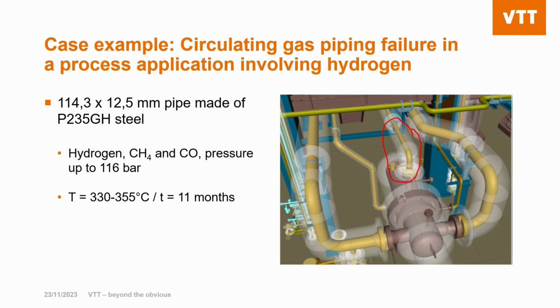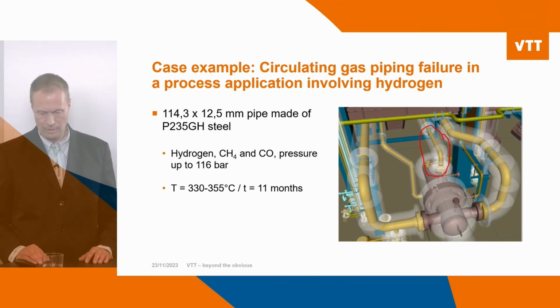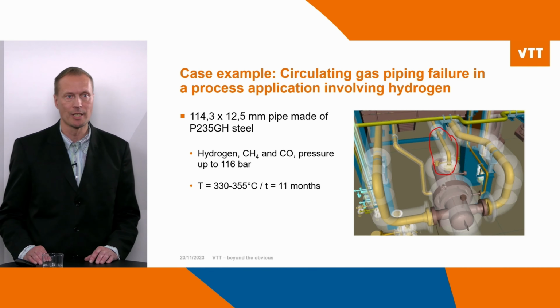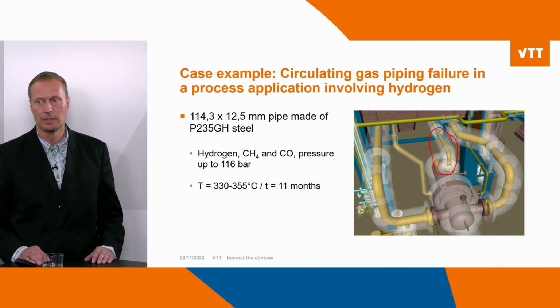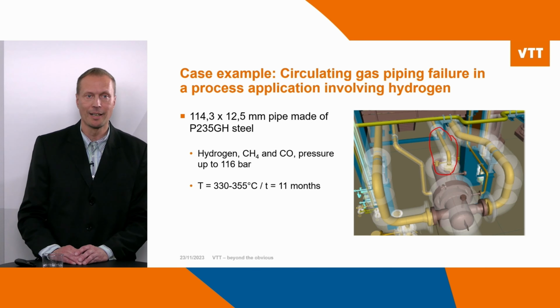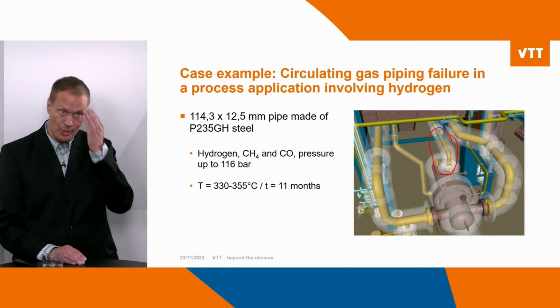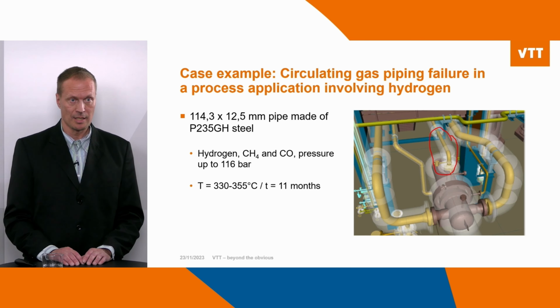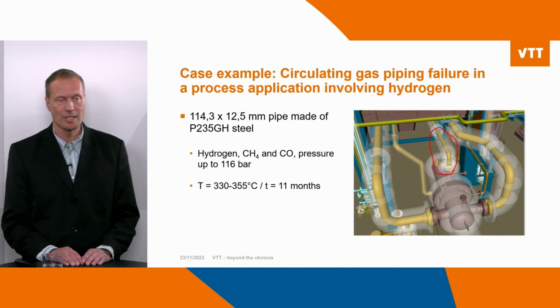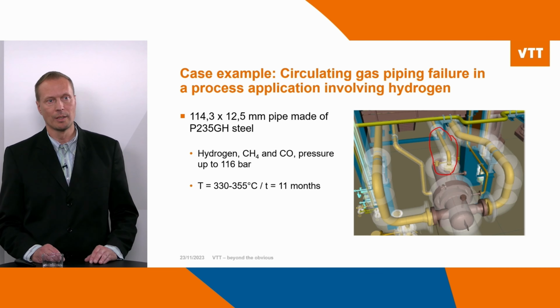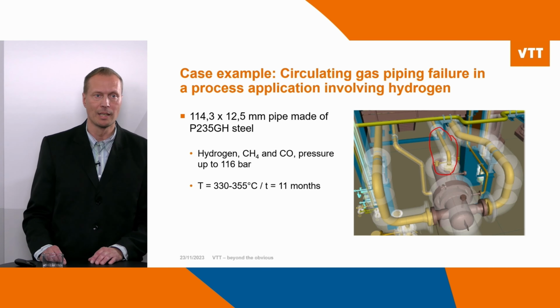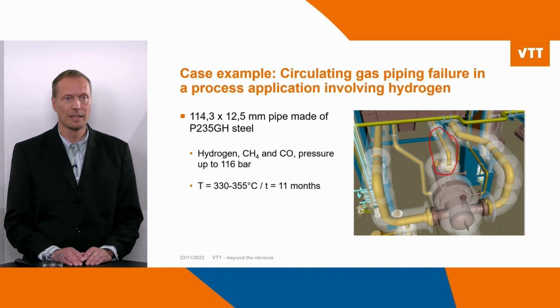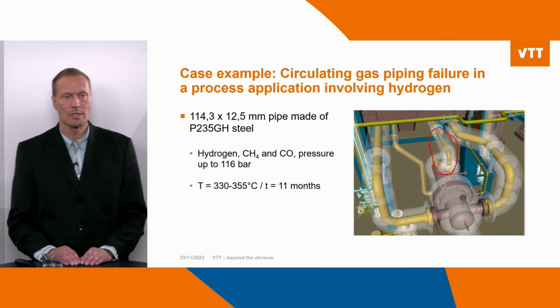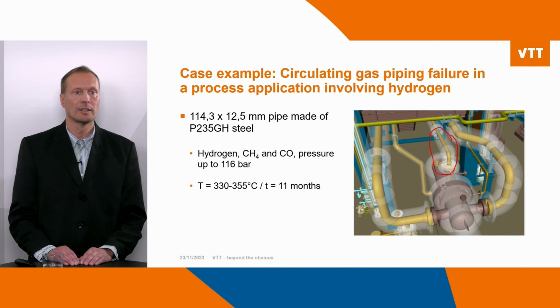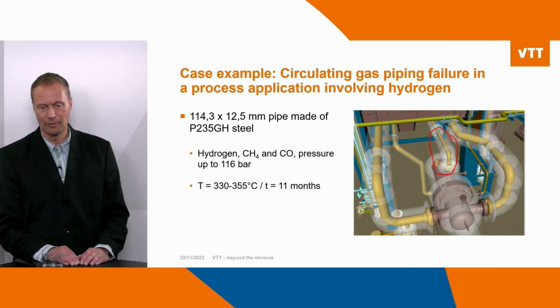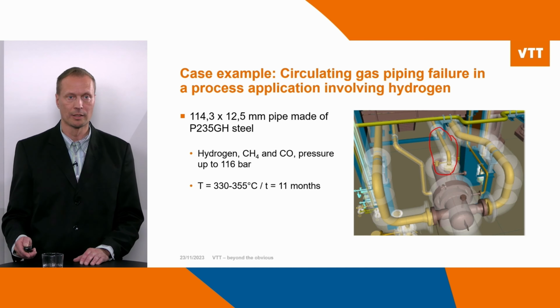Then I'm going to present an industrial case example where an older plant which has been converted to hydrogen service has suffered from severe high temperature hydrogen attack. In this example, circulating gas piping failure had occurred in a process application which involves hydrogen. The pipe that failed in this case was a carbon steel P235GH steel with outer diameter of 114.3 millimeters and with a wall thickness of 12.5 millimeters. The process included hydrogen, methane and carbon monoxide, and the process pressure was up to 116 bars. The temperature was from 330 to 355 degrees Celsius and time elapsed was 11 months.